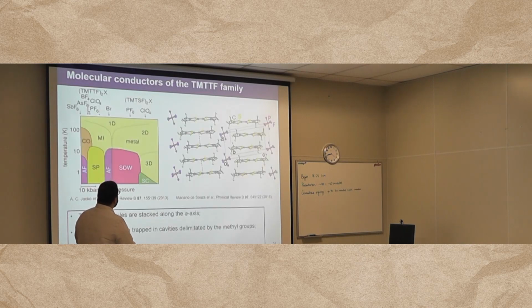So why are these TMTTF family conductors important? First, their phase diagram is very rich. So we have here a temperature versus pressure phase diagram. We have a charge order phase, a metal insulator transition, antiferromagnetic, spin-Peierls, which is a non-magnetic phase. We have spin density wave, we have superconducting, and we have the crossover from 1D to 2D to 3D, and of course a metal. And each of these systems is composed of two molecules.